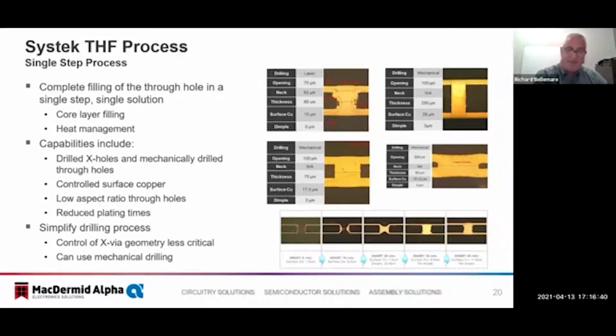This process is applicable to panels of upwards of about 0.6 millimeters thick, though it is preferred in applications of less than 0.4 millimeters. It can fill very low aspect ratio holes and consistently reduce plating times by 50% or more. The primary application for this system is the through-hole filling of core layers for further stack buildup and heat management. And that's all I had.